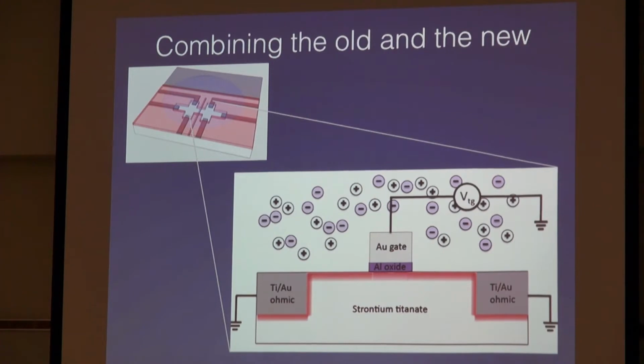But what I want to talk about today is this hybrid approach we've started doing to create nanoscale devices in STO. And I'm going to talk a little about the interesting transport properties that we've seen in the system. What we've done is we've actually combined the old and the new. We've combined the ionic gating with conventional metal gating. And what that's allowed us to do is actually have very precise control over where the ions go. This is more a lithographic technique, I think, than anything else. It may have some future use if you need to make devices out of this. The ions are very slow. They don't make good RF devices, so creating these hybrid structures where you induce an electron gas and then you change its properties quickly, anyway, that's down the road. But what we use this for is more lithographic.